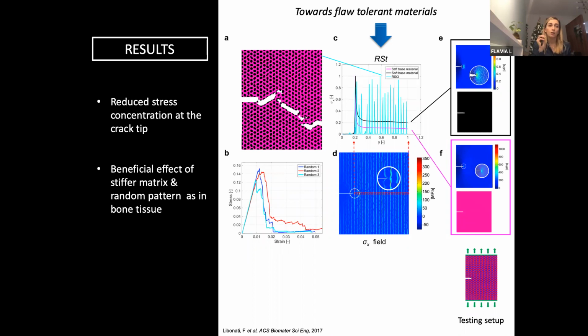So after validating this numerical tool, what we did was try to expand the design field and change the topology. In this case, this was just an initial attempt which could be further expanded by optimization studies. We combine both the circular and elliptical holes and consider random distributions with random orientation, keeping the center of each one constant, so through our triangular lattice, and keeping also the hole volume fraction constant in order to be able to compare with the previous study.